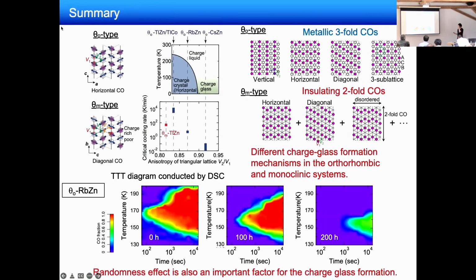Okay, so this is a summary of my talk. In this presentation, I compared optical conductivity and resistivity in these three different materials, and we found different charge glass formation mechanisms in the orthorhombic and monoclinic systems. We also found that the randomness effect is also a very important factor for the charge glass formation.